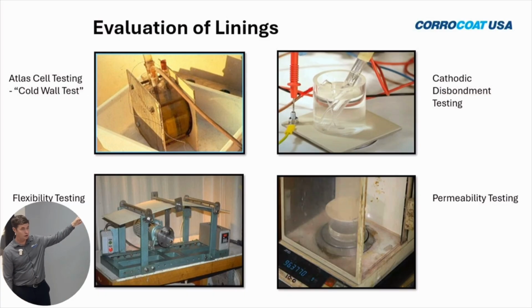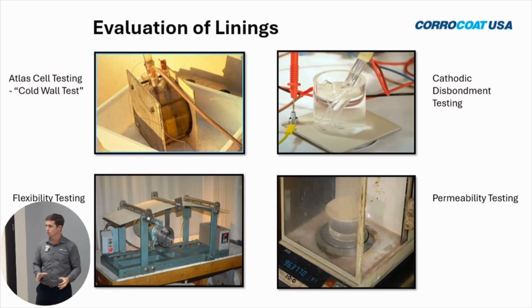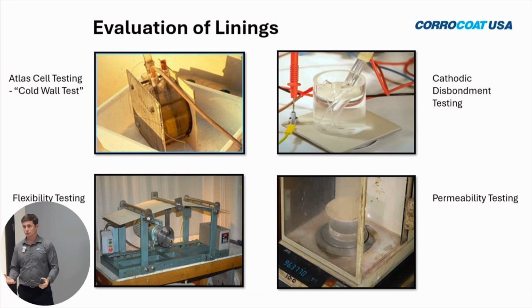So we'll do the cold wall test. Has anybody heard of the cold wall test? An Atlas cell test? No. The cold wall test utilizes coated plates and a translucent tube. The beauty of this, particularly when you're testing for high pressure or high temperature and chemical, is you can put a given chemical in there. You can put the exact same chemical in there to mimic the environment, alter the pressure and alter the temperature to ensure that you can handle that.